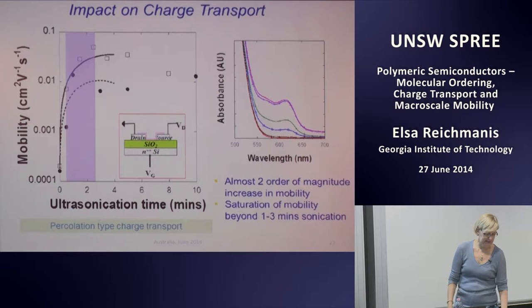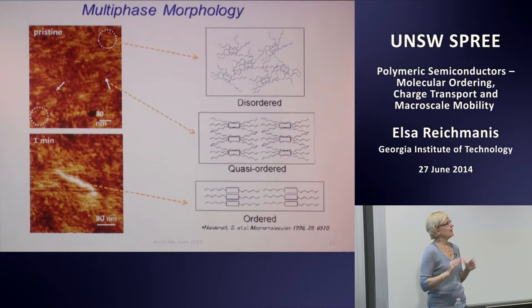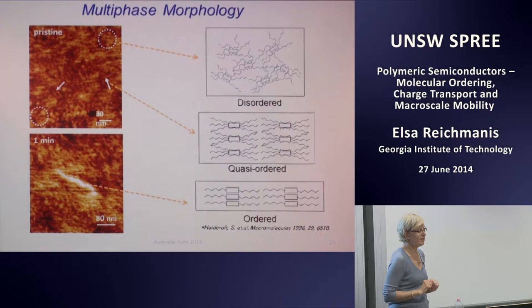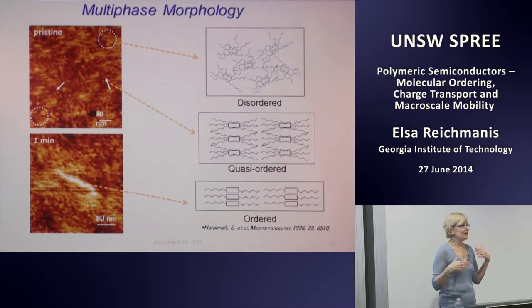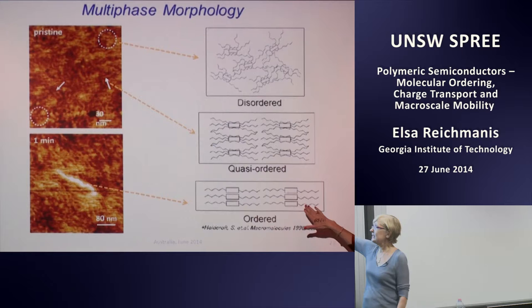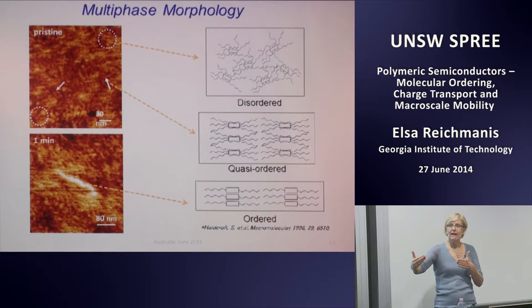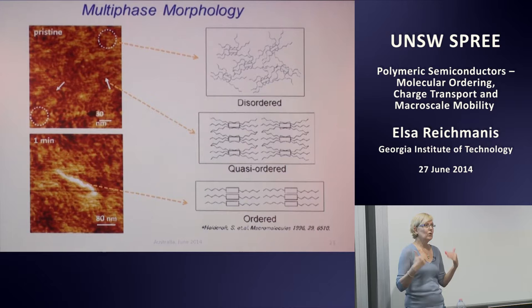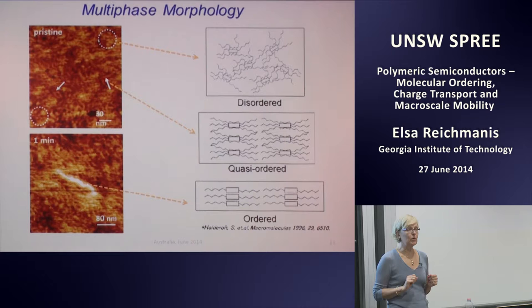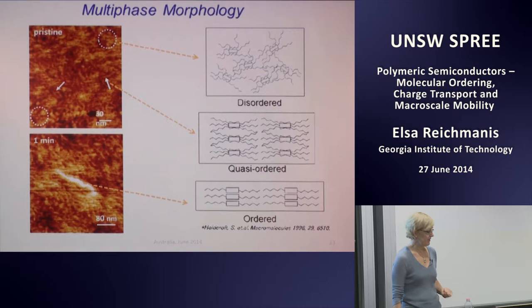So the multi-phase morphology appears to be very important in charge transport in P3HT. And it's actually something that Steve Holdcroft had predicted almost 20 years ago now, when he was looking at some initial studies on P3HT and predicted that transport within the material is a function of highly ordered states, quasi-ordered states, and also disordered regions within that system. All right, so ultrasonication is one way to induce molecular ordering in P3HT prior to deposition of the thin film.